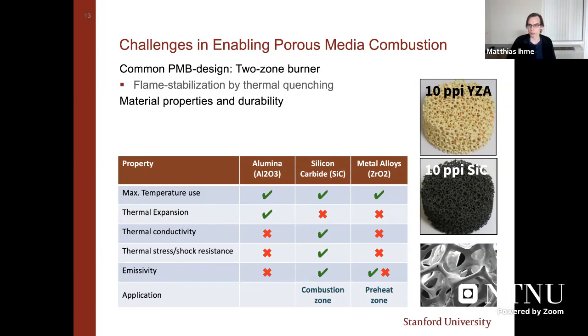So to give you an idea here for the different systems, these are a couple of samples that we typically use, an yttrium stabilized zirconia. The diameter is about 5 centimeters in the cross section, and the pore size, as I said, is somewhere around 5 millimeters. The key parameter here is the units of PPI. I'm sure that you are very familiar with this. These are 10 pores per inch. We are here in America. We like to use units of inches. So this really translates to a pore size of around 2.5 millimeters. And the same is true for the silicon carbide, right?